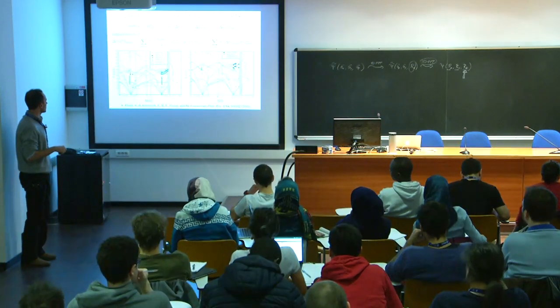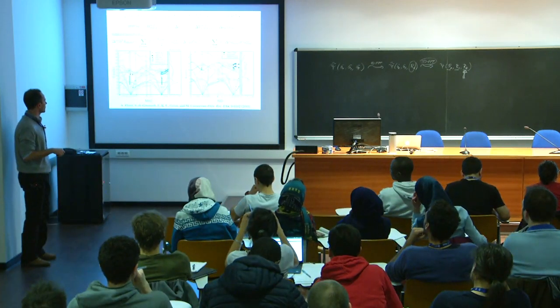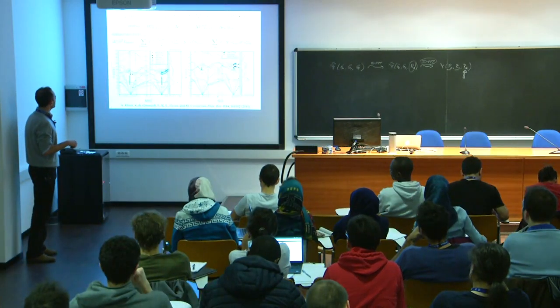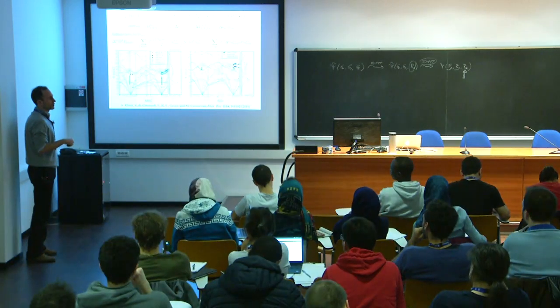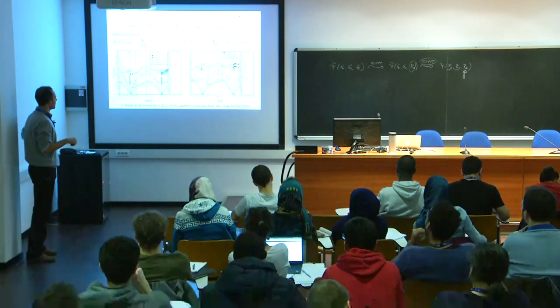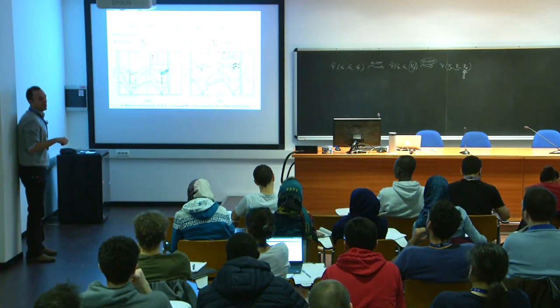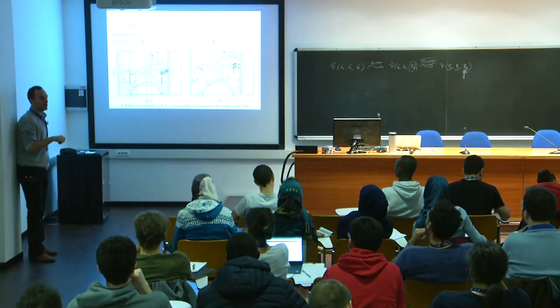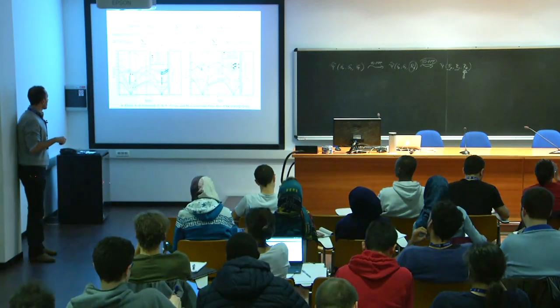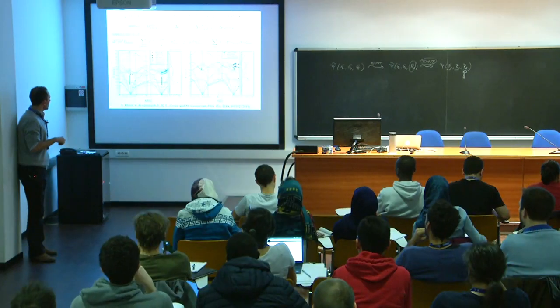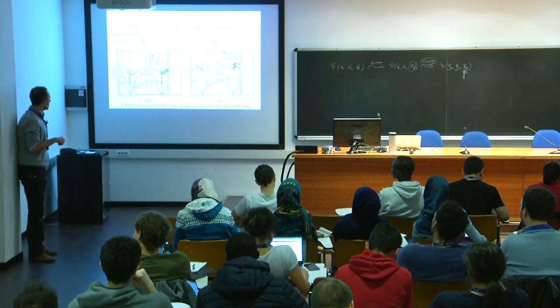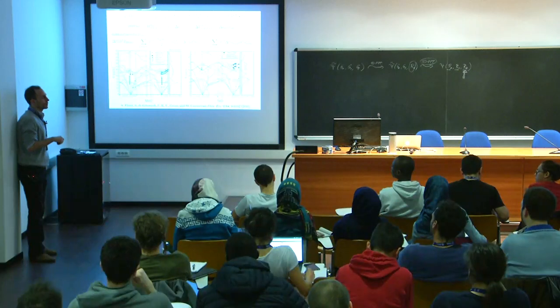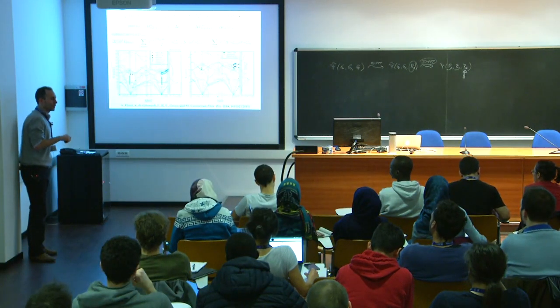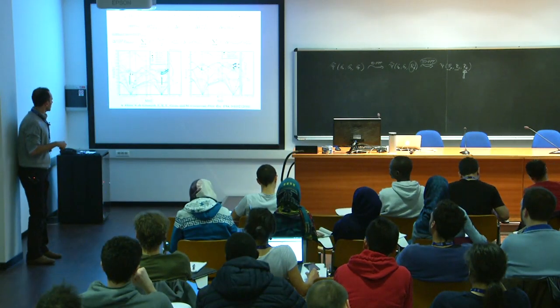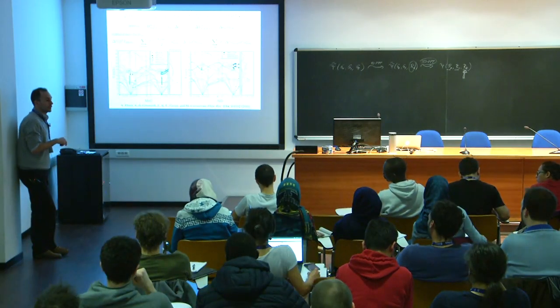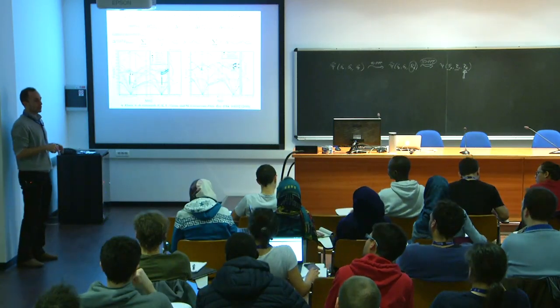Again, these are two transition metal monoxides, manganese oxide and nickel oxide, and you can see that the DFT GGA results are the black dashed lines, and the green solid ones are the results obtained with the U correction. So you see a significant shift in the vibrational energies of these materials. Specifically, you see these big jumps, the correction of these big splittings between transverse optical modes that you obtain with DFT. These are due to the magnetic interaction, that because of the delocalization of electrons is overestimated in DFT.